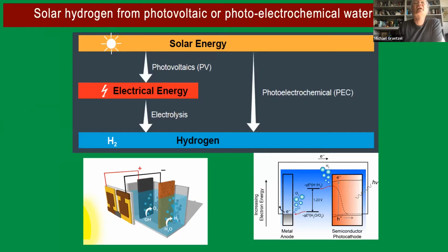And so how do you make hydrogen from sunlight? You can do it in two ways. Either you use a photovoltaic cell and combine it with an electrolyzer. And so that, for example, is shown here. You have two perovskite cells in series connected to get the higher voltage you need. And you add the voltage of the two, and then you get about 2 volts at the maximum power point, maybe 1.8, and that's enough to drive the electrolysis of water at the photocurrents which you draw from in full sunlight.